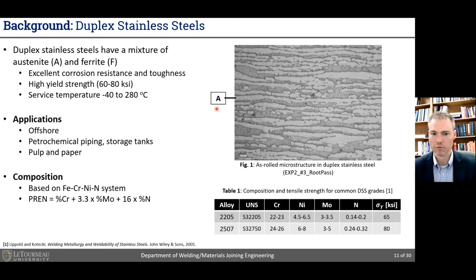It has excellent corrosion resistance and toughness, high yield strength depending upon the specific grade, and service temperatures from -40 to roughly 280 C as the upper limit. The corrosion resistance is the prime benefit for these materials over, for example, austenitic stainless steels. Greatly improved chloride corrosion resistance, so finds applications in places like offshore, petrochemical piping, pulp and paper.